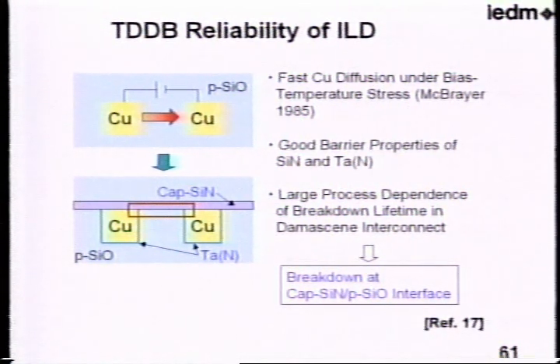Also, this is very serious for interconnect scaling. The fast copper diffusion under bias temperature stress was reported in 1985. To prevent this kind of fast copper diffusion, we put a good barrier around the copper, like tantalum nitride and capping SiN. But the problem is not completely solved by using cap layer and barrier metal, because at this moment the breakdown point is not between the lines, but the interface between the copper capping layer and ILD.